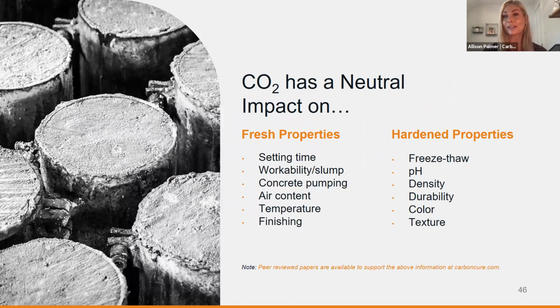Like I mentioned, CO2 has a neutral impact on the fresh and hardened properties of the concrete. In fact, if we didn't tell you CO2 was being used, you would not be able to tell. It has the same set time, workability, pumpability, temperature, finishing, no impact on air content, and can be used with any admixture, aggregate, cement, SCM. Hardened properties like freeze-thaw, pH, density, durability, and color are also unaffected.